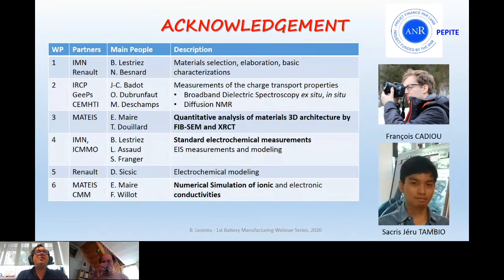Yes, no problem. Have you experimentally found a way to reduce these PVDF CB agglomerates? Okay, the point is that we haven't made these electrodes ourselves. They were provided to us by Renault. So I guess it should be possible, because this is something which is not usual to observe in electrodes. What is interesting, finally, is that it tells us that we can even put less CB-PVDF than was put in these slurry recipes to achieve good performance. This is what I can say.